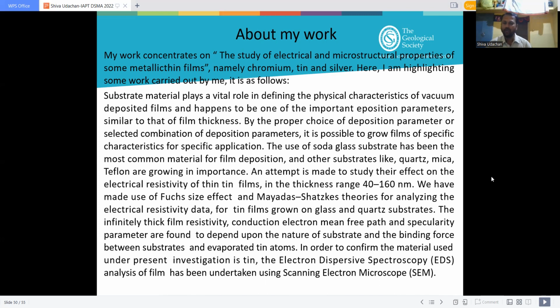We have made use of Fuchs size effect and Mayadas-Shatzkes theories for analyzing the electrical resistivity data for tin films grown on glass and quartz substrates. The infinitely thick film resistivity, conduction electron mean free path, and specularity parameter are found to depend upon the nature of the substrate and the binding force between substrates and evaporated tin atoms. In order to confirm the material used under present investigation is tin, energy dispersive spectroscopy, that is EDS analysis of the film, has been undertaken using SEM, that is scanning electron microscope.